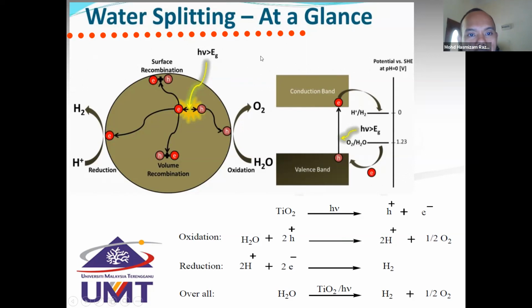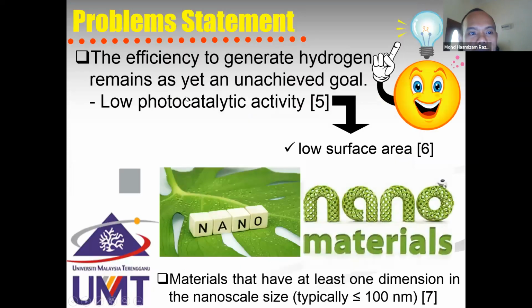But somehow, currently, the efficiency to generate hydrogen gas remains low. That means the photocatalytic activity of common or commercial titanium dioxide is very low due to its low surface area. So we came up with a material that has at least one dimension at the nanoscale, between 1 to 100 nanometers. So we focus on nanomaterials.